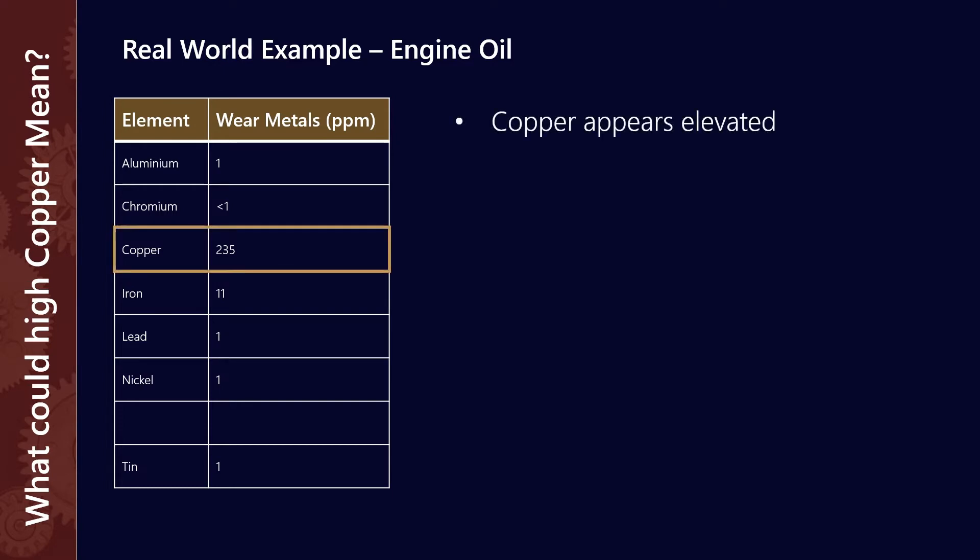It's 235 parts per million and most likely if I were using any kind of lab whether that be third party or one of the lubricant manufacturers it would probably be an alarm. On the other hand all the other elements appear normal. So we really want to get some more sample history to place this particular result in context.